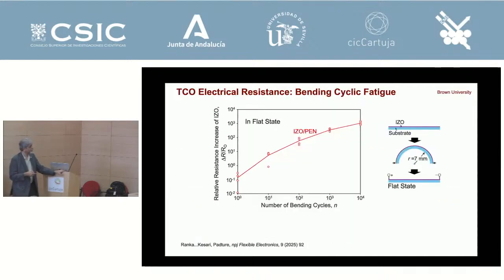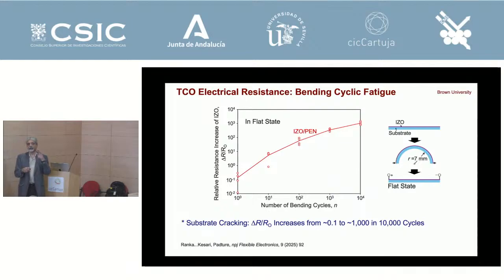Okay, and so I just have a couple of slides here. We measured the resistance of this ITO or IZO as a function of the number of cycles. Over 10,000 cycles, measured in the flat state, the resistance goes from 0.1 to about 1,000. So that's 4 orders of magnitude increase in resistance with no interlayer, correct?